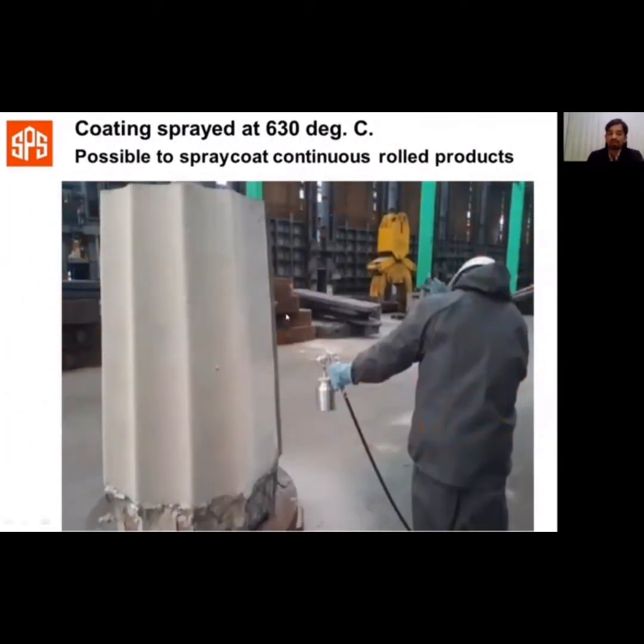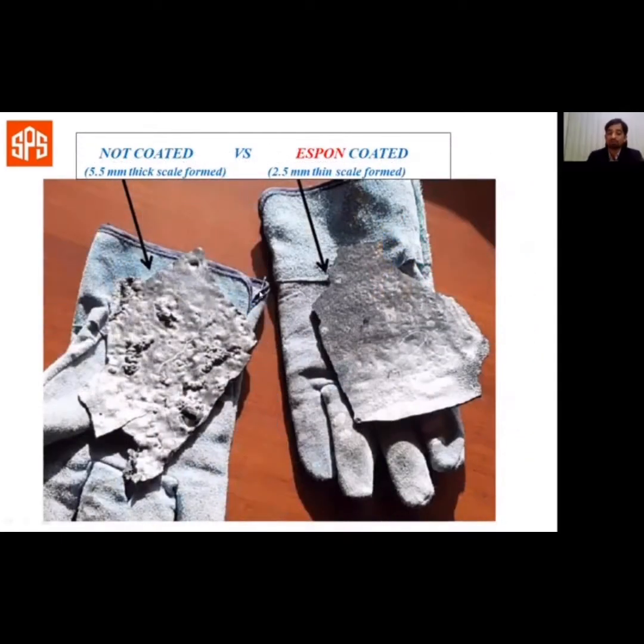Coating can be sprayed at high temperatures too. This is an ingot at 630 degrees Celsius being spray coated. The same can be carried out for continuous cast hot rolling mills as well. And finally, the result of coating.